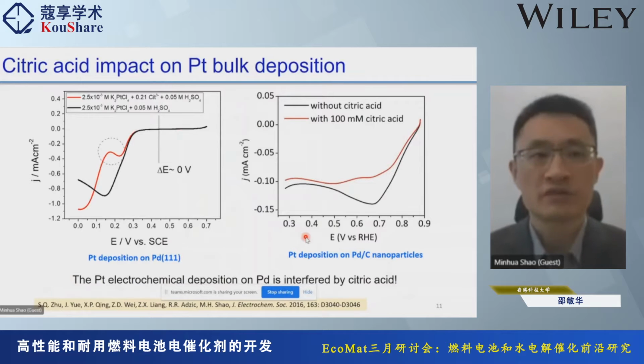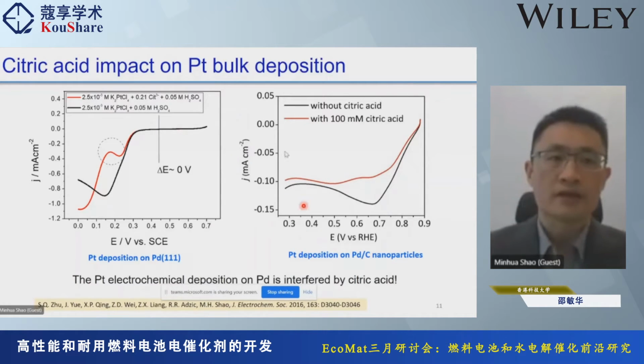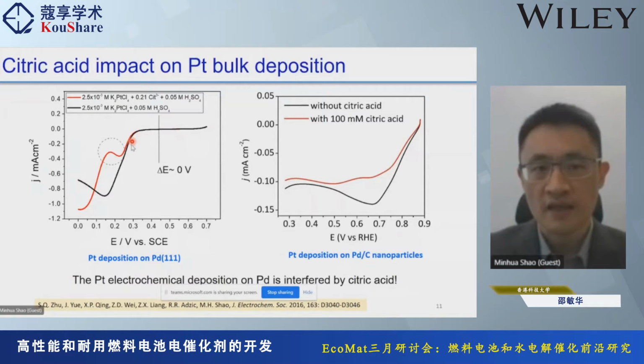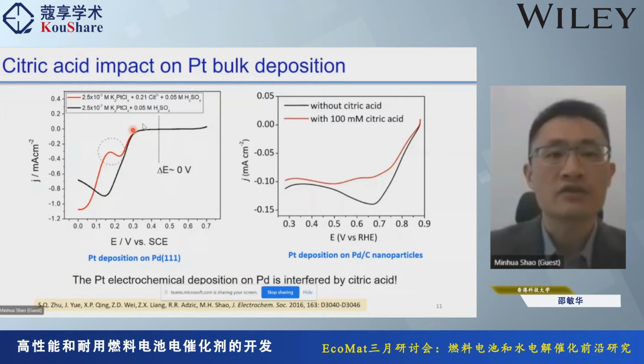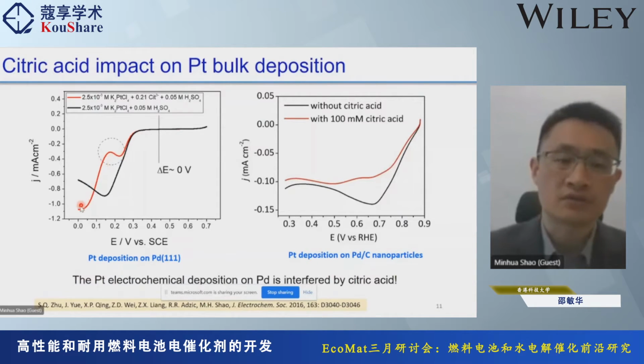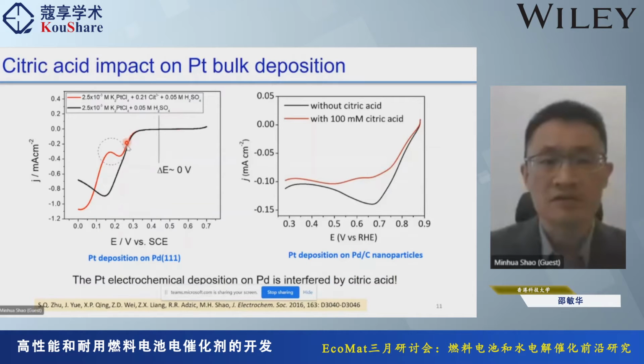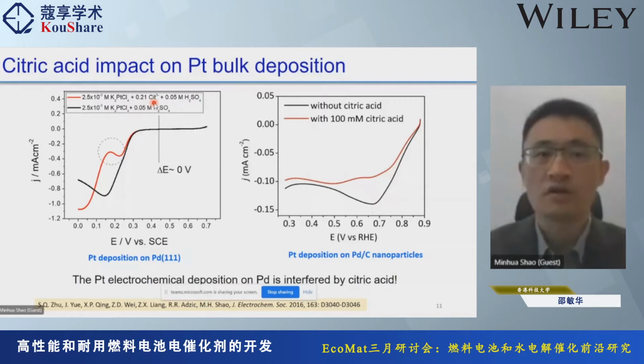So what we did here is we put some citric acid in the deposition solution. First we did some experiments on single crystal palladium 111, the platinum deposition on palladium 111. That's the black curve, the regular normal curve. You start the deposition and there is a regular peak. But if you have some citric acid in it, you will see that the deposition starts at the same potential, but it is inhibited at a certain potential, and then the deposition starts to continue again. So that means the platinum deposited on the surface actually inhibits further deposition of platinum, because of the citric acid, which has a specific adsorption on the platinum surface.